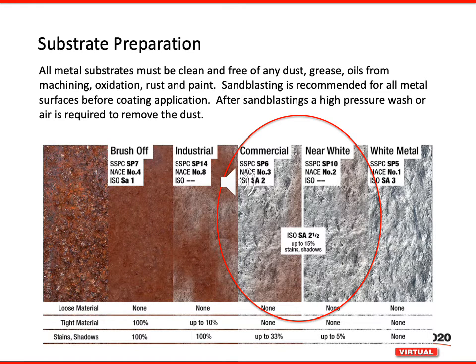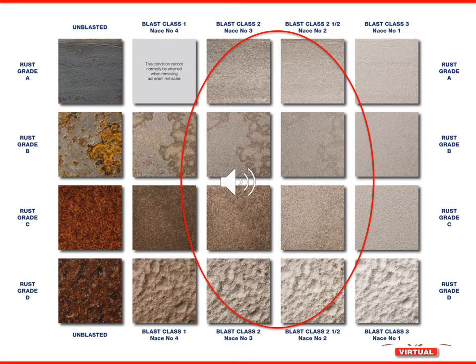Surface preparation by far is the most important step in any coating application. All metal substrates must be clean and free of any dust, grease, oils from machining, oxidation, rust, or paint. Sandblasting is the preferred method of cleaning, and it is recommended that a commercial or near white blast be performed to prepare the surface. The chart on this slide gives a visual description of the substrate requirement prior to any application of a ceramic coating.